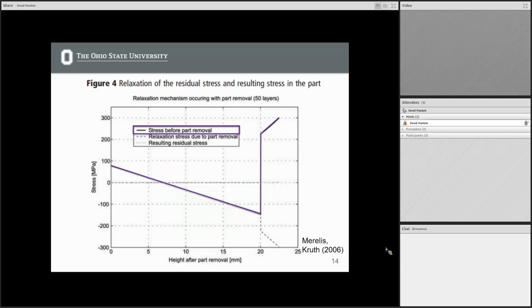So one important thing to note here is that this is our yield stress, and that's through that assumption that we applied at the very beginning that the uniform shrinkage is going to cause yield stress in the top layer of the part. So then this is our relaxation mechanism that we just showed the equation for. So we're going to have our uniform shrinkage and then our bending. And then this is going to be the resulting stress after we actually cut the part off of the base plate itself. Now this looks like a pretty much horizontal line.